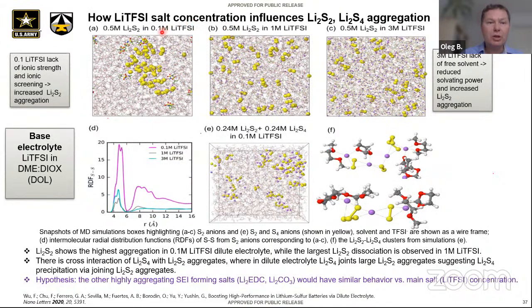Once I decreased salt concentration, essentially all Li2S4 went into one cluster. A very highly aggregated system. At high concentrations, there was also increased clustering. Typically in this area, there is a lot of work from Watanabe, where high concentration was attributed to reduced solubility and high aggregation, because what happens is you put in more salt, and each lithium takes a solvate, gets solvent to be solvated. So you are exhausting, or you have a very small number of, available free solvent to solvate the other salt which you're introducing, right? So that's typically the explanation provided for the high concentration.